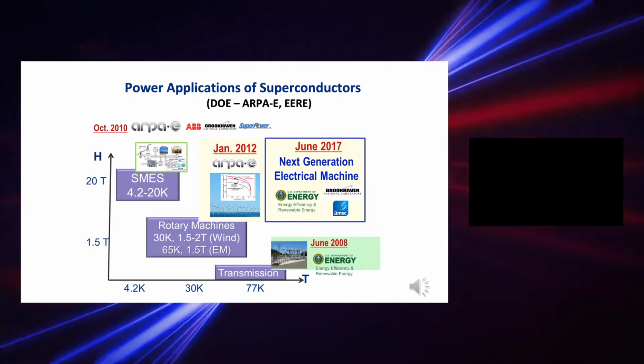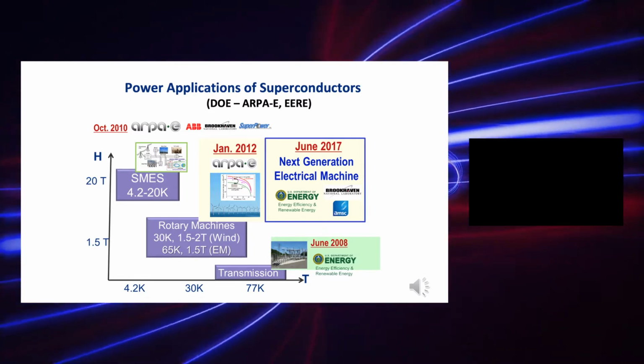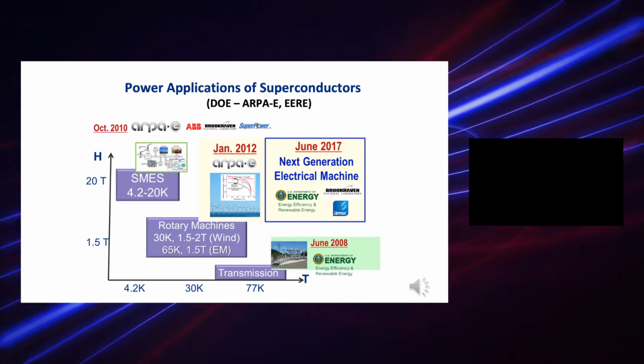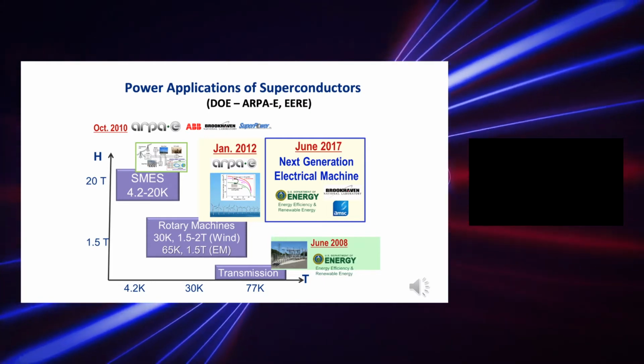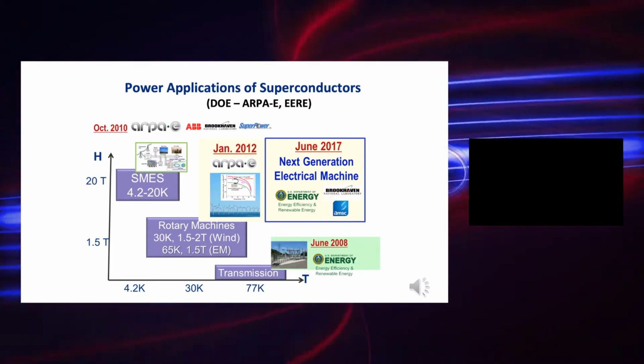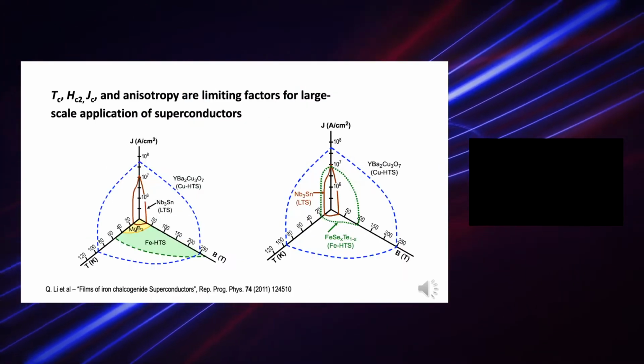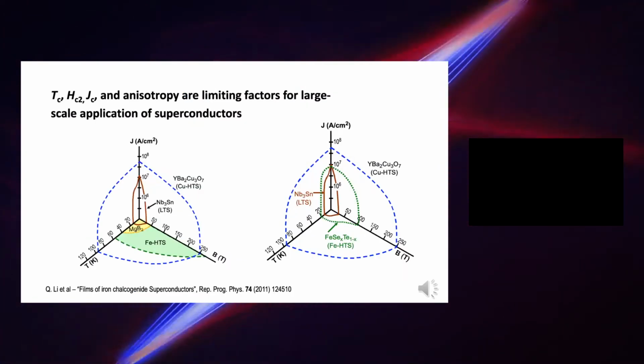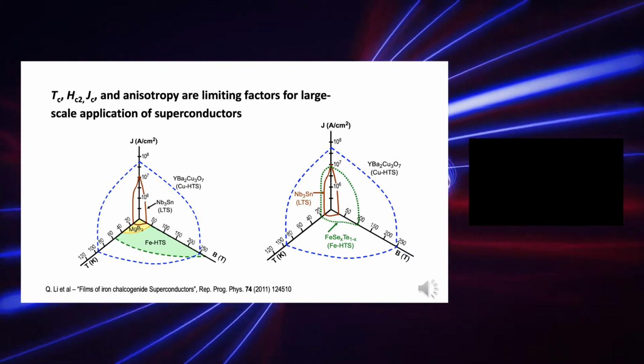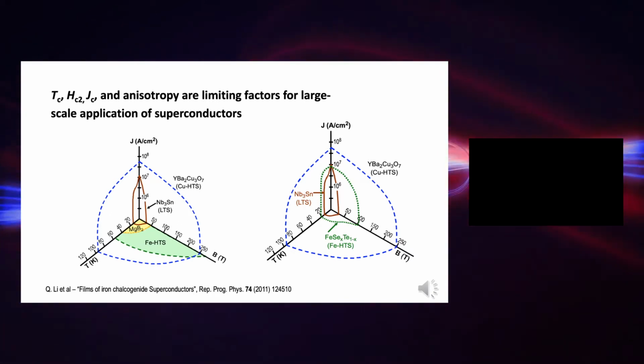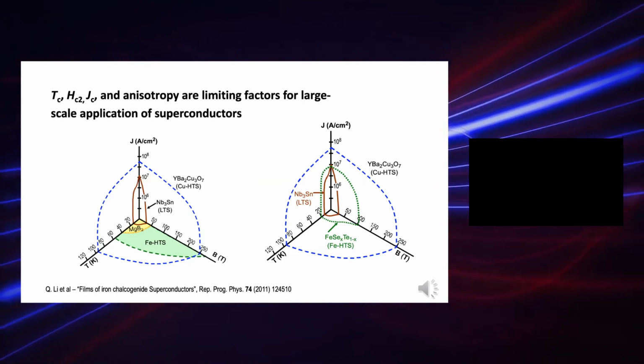As you can see, each application occupies a specific area of the phase diagram, with the magnet energy storage mostly applicable at a lower temperature and higher field. And for transmission lines, at a moderate field and higher temperature. Rotary machines occupy the middle section of that. As we know, the TC, HC2, JC, and anisotropy are limiting factors for large-scale application of superconductors.